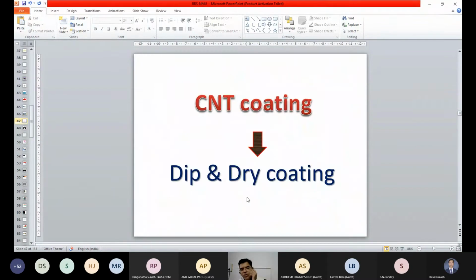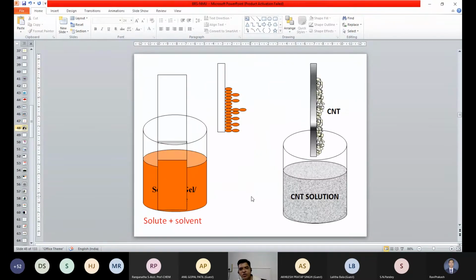So how have we done the carbon nanotube coating? Simply, you can think of the dip and dry coating technique. So what does dip and dry coating mean? Actually, this is an animation. You can use a solution of the carbon nanotube, and then you dip the substrate inside the carbon nanotube solution, so that when you take out the substrate, the carbon nanotube is coated on the substrate surface.